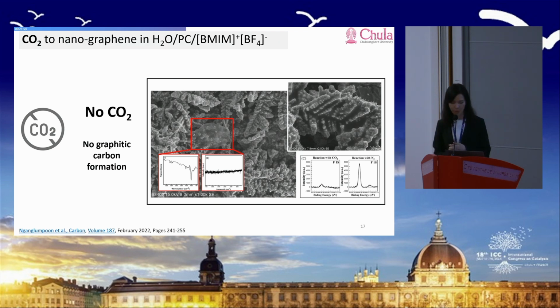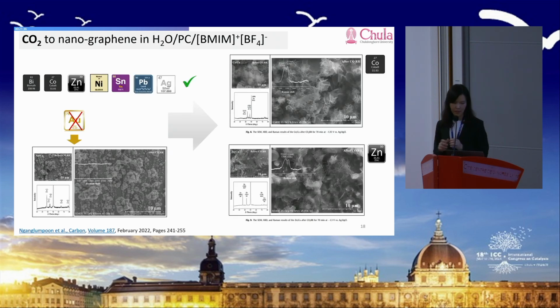And how do I prove that it comes from CO2? Later on we proved more, but at that time, if we don't have any CO2 gas in the system and we just try to reduce our electrolyte, there's no carbon formation, so almost no reaction at all. We have tried different metals here: bismuth, cobalt, zinc, nickel, tin, lead, silver. We were able to reduce carbon dioxide into graphitic carbon materials. The exception is gold, which we tried under different conditions and were not able to get the same results. And what's the difference here? Gold is less oxyphilic than the others. So we are thinking that there may be some clues from the presence of oxide layers